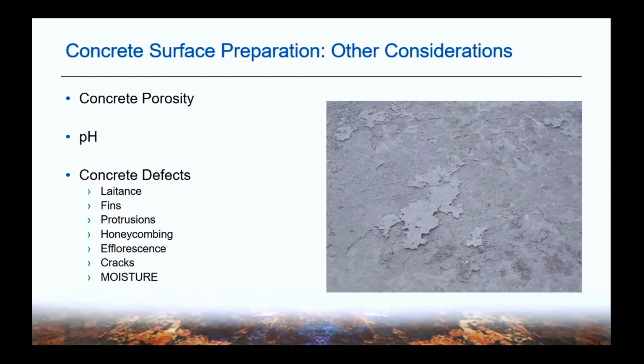There are also several defects in concrete with finishing that need to be prepared and need to be removed and filled. One of these, this picture here on the right, is laitance. This is in essence a weak unreacted layer of paste that's left on the surface, and over time, that's going to end up releasing from the surface. I've seen quite a few times through the years where the contractor did not remove that laitance, and in turn coated over the top of it. Then over time they ended up having issues, and that coating system did not last like it should have.